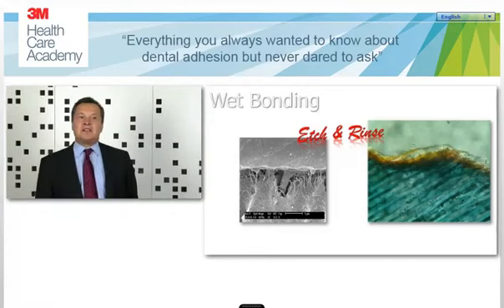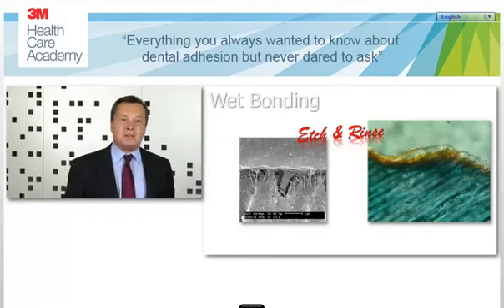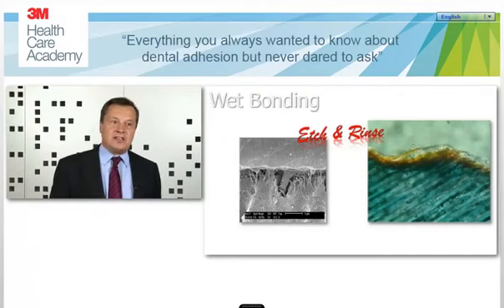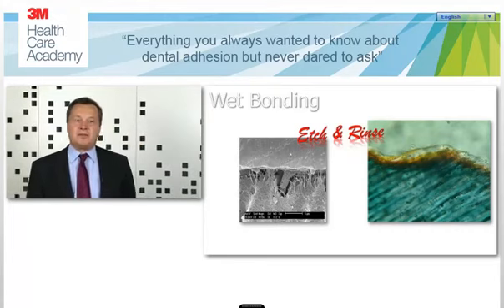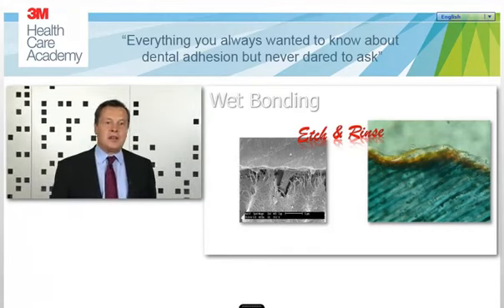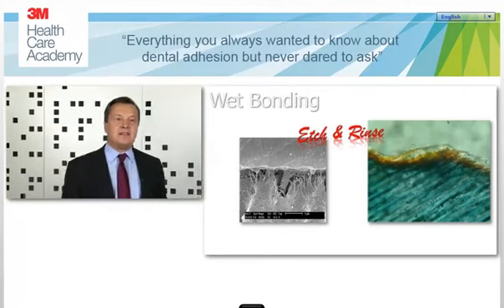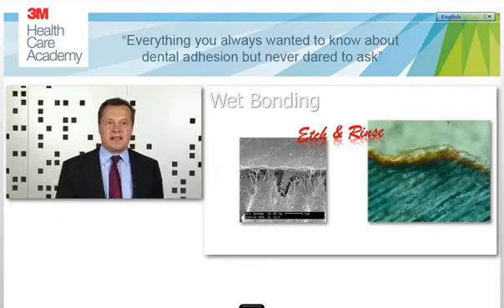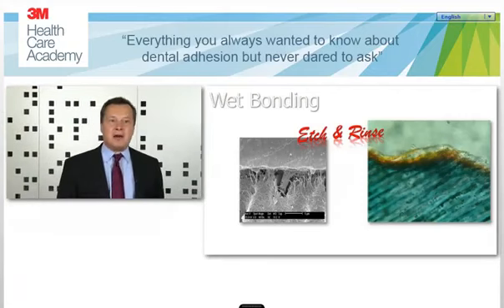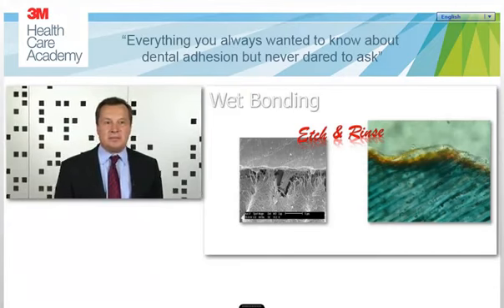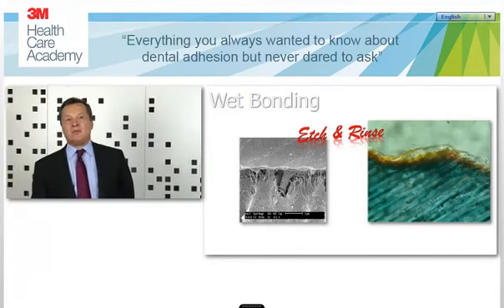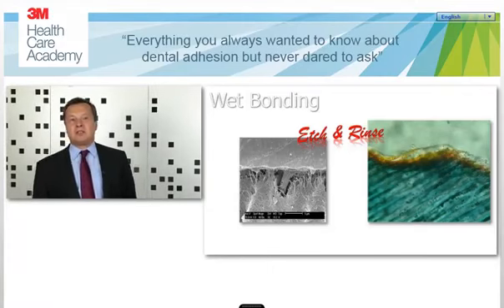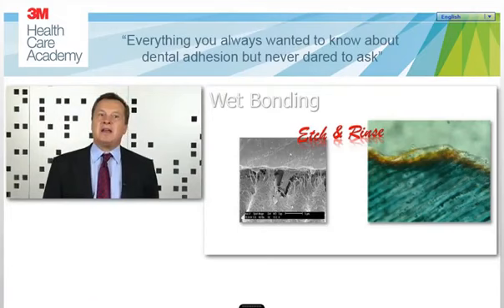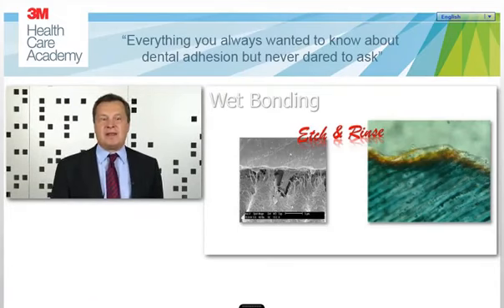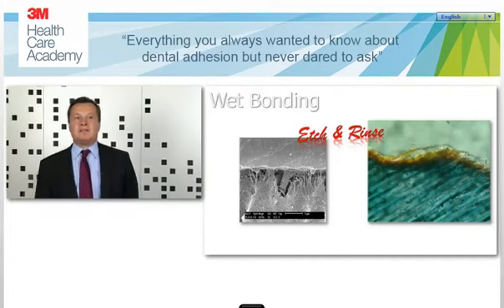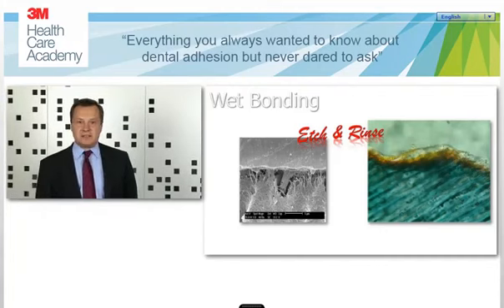The problem of the situation is the fact that then you have to perfectly penetrate this demineralized collagen layer to get a good adhesion. And very, very often, this is very difficult or almost impossible. As you can see in the picture on the right-hand side of the slide, there is a thin brown portion of dentin, which was stained with a brown colorant and which shows exposed collagen which was not perfectly penetrated by the primer and by the bonding of this adhesive system. And this might occur, especially in conjunction with etch-and-rinse adhesive systems.